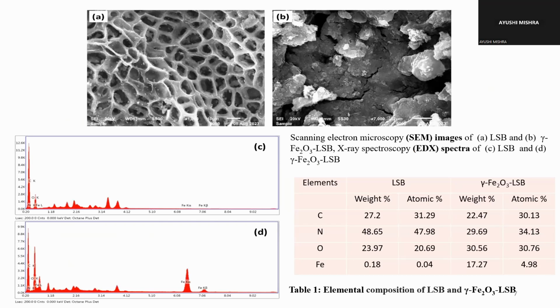These are the SEM images of biochar and magnetic biochar. We can see a rough, porous surface on the magnetic biochar. In the EDX spectra, we can also observe an increase in the Fe, the iron content, that also shows the magnetic nature of the magnetite biochar.